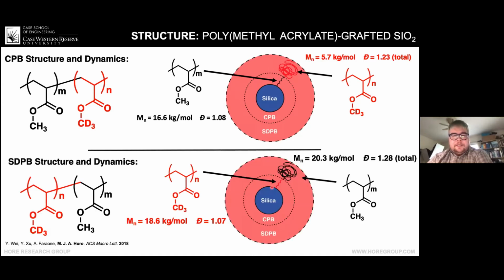With the reverse case, we're going to measure the opposite, but in this case, we wanted to match the molecular weight of the inner region to that of the previous sample. And then since we are scattering from the polymer chain out here, we did increase its molar mass. And you can see the characteristics of the polymers are quite similar.